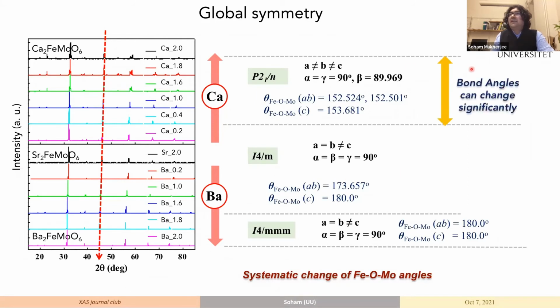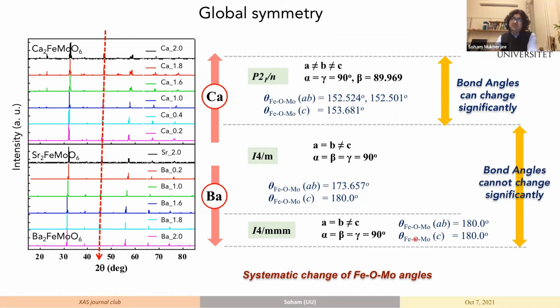And you will see that here, the bond angles, these are all calculated from diffraction. They can change significantly. The angles are close to 150, 153. But on the barium side, in this region, the change of angles is very, very little. So you can go from a lower symmetry tetragonal phase to a much lower symmetry monoclinic phase, and by doping in higher, you go to a higher symmetry tetragonal phase. So all by the change of iron, oxygen, molybdenum bond angles.